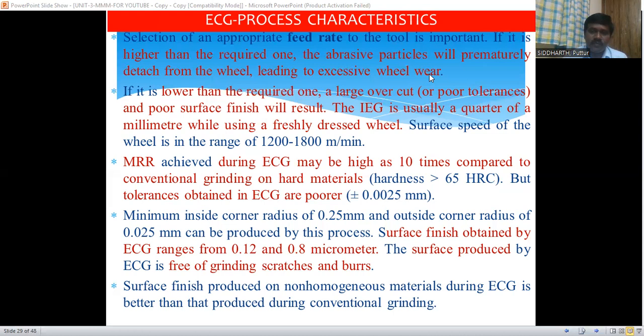A minimum inside corner radius of 0.25 mm and outside corner radius of 0.025 mm can be produced by this electrochemical grinding process. The surface finish obtained ranges from 0.12 to 0.8 micrometer. The surface produced by ECG is free of grinding scratches and burrs. So no burrs or scratches will remain on the surface of the component machined by this process. The surface finish produced on non-homogeneous materials during electrochemical grinding is better than that produced during conventional grinding.